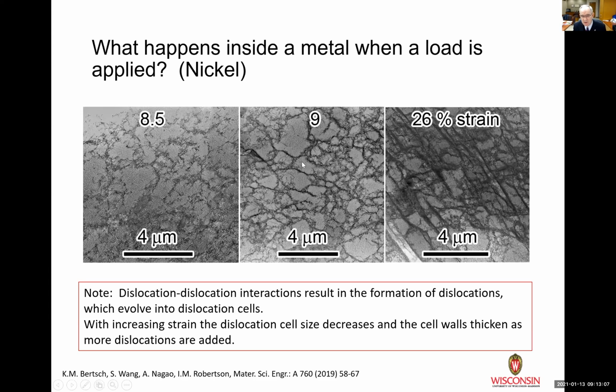And you can see some of them are different orientations. The cell boundaries are making cells of different size. And as you keep straining, you will refine the grains, this cell size, to smaller and smaller sizes. And that's what you see at 26% strain. You'll see much smaller cells.